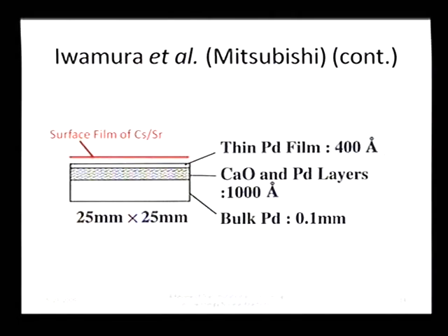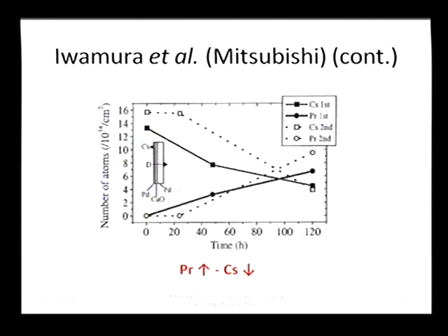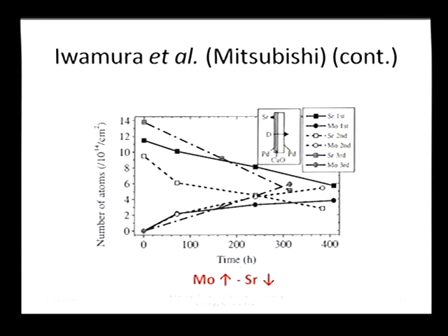The structure of the film was basically a bulk palladium material of about 0.1 millimeter thick and about 1 inch by 1 inch. There was a calcium oxide layer, and then thin film of palladium, and then a surface film of cesium, and a separate experiment with the surface film of strontium. The observation was that as time went on during the experiment, the cesium level decreased and a praseodymium atom or element increased with time. And if you look at the other experiment with strontium, it was molybdenum being the element that was created and strontium levels decreasing.